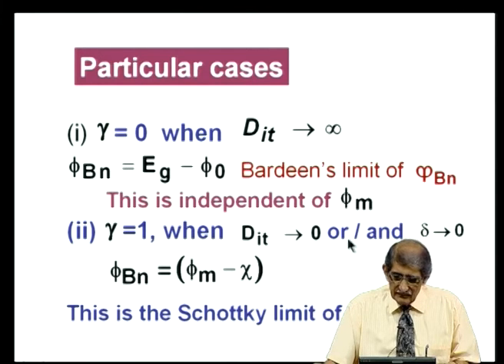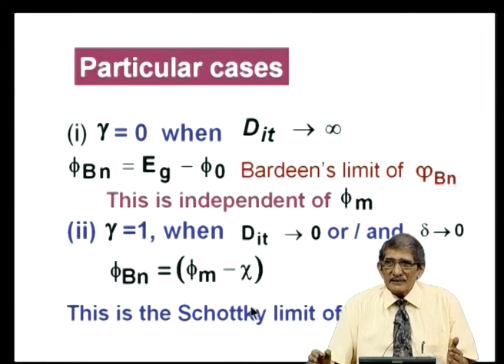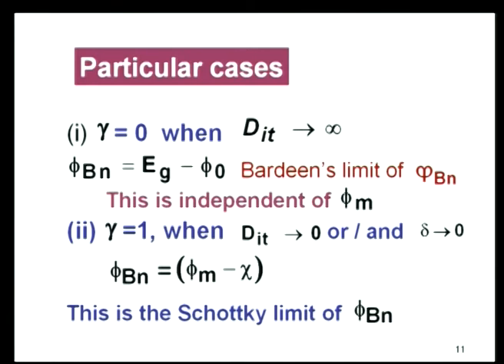Gamma equal to 1, D_IT equal to 0 or delta equal to 0, ideal, phi_m minus chi. That is called the Schottky limit, because Schottky and Mott gave the theory of the Schottky diode and a barrier, saying that phi_m minus chi is the barrier. So, ideally, the Schottky limit is on one extreme end, and Bardeen's limit on the other. Now, you can see if it is ideal, then you can vary the phi_m and vary the phi_bn, but it does not happen. But in the worst case, phi_bn is equal to E_g minus phi_0.